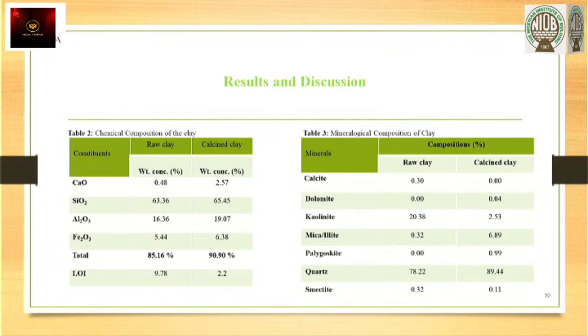Results and discussion. Table 2 shows the chemical composition of the clay. From the results, you can see that the silica content in the raw clay material was 63.36%, and the other oxide present in considerable quantity was alumina, which is aluminum oxide, at 16.36%, followed by iron oxide with 5.44%. And the total aggregated sum of the silica, alumina, and iron oxide of the raw clay and the calcined clay were found to meet the requirements of